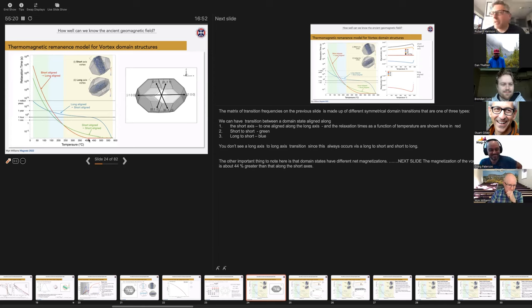So, so that's what happens at fast cooling rates. At very long cooling rates. Then everything is essentially unstable on the million year timescale until you get down to whatever this is 140 or 130 degrees. And the first energy barrier that comes across, the first thing that becomes stable are these short aligned grains. So, anything that finds itself in a short aligned axis can't easily move out into anything else. And the long aligned actually doesn't become stable until about room temperature. So, that's an extreme example. I mean, not many things will cool at time scales of millions of years, but it's an extreme example, but the exact position of these different relaxation curves essentially defines how the proportion of the domain states are distributed among the different available domain states, depending on how quickly they move through this decision point, if you like, of the different domain state frequencies.